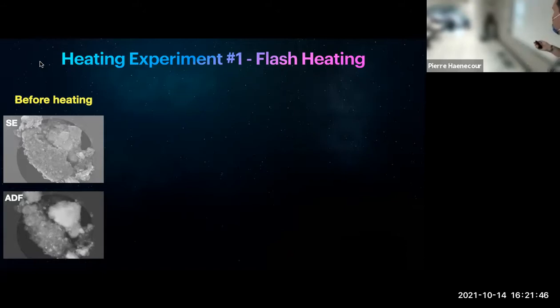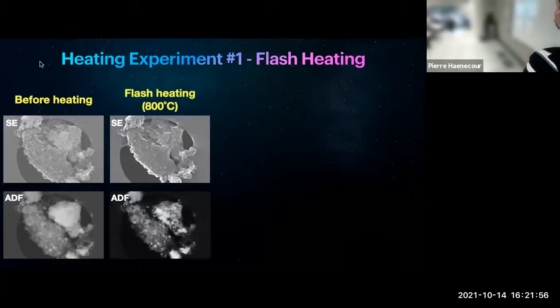And you can see here, those two images, both the secondary electron and dark field, ADF is for annular dark field images, are showing you before we did the heating. Then you can see that after the flash heating, the surface actually looks a lot different. It shows that there is a lot of melting happening. And we can see that even inside of the sample, there is a lot happening. You see the contrast change a lot. So it clearly did affect the sample.